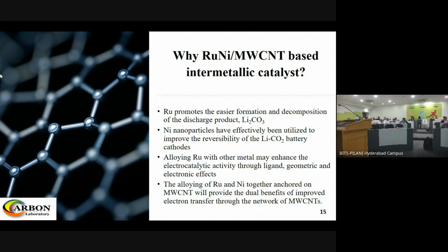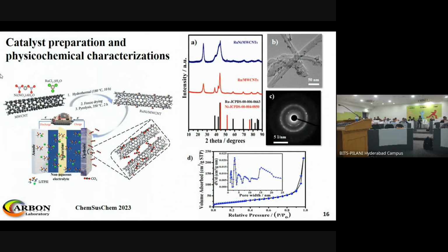So now we are alloying this ruthenium with another metal to enhance the electrocatalytic activity through ligand, geometric and electronic effects. And we are anchoring this ruthenium nickel alloy on the multi-wall CNT for better dispersion, to provide improved electron transfer. That is the goal of this particular synthesis of ruthenium nickel on multi-wall CNT. For the synthesis, we took nickel salt, ruthenium chloride and multi-wall CNT, did a hydrothermal process under certain conditions, and pyrolysis at 350 degrees Celsius. This is how we decorate the ruthenium nickel nanoalloy bimetallic catalyst on the multi-wall CNTs, and then use it as a cathode catalyst support on the carbon cloth, which is used as the cathode.